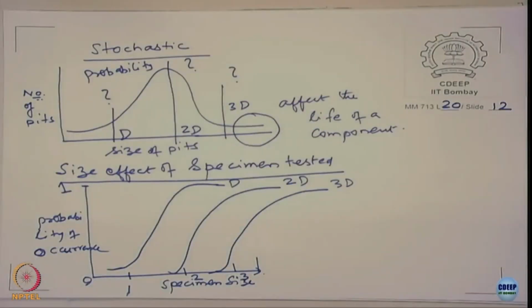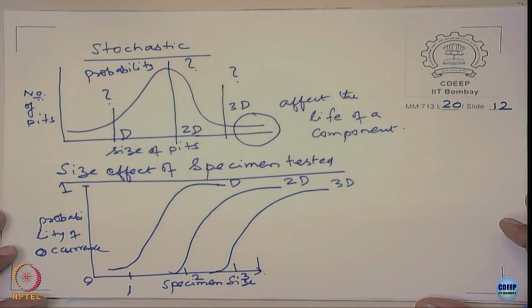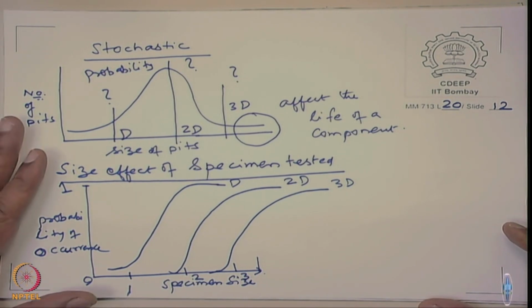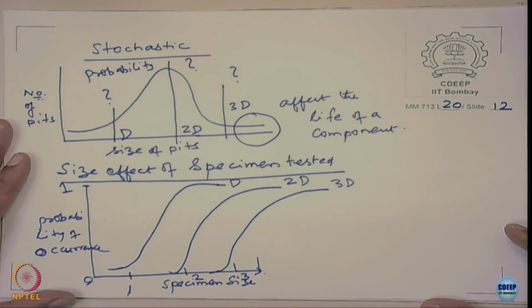So this is one aspect, and people have in fact dealt with this. The probabilistic theory of pitting corrosion has been one of the important topics of research. We will not go into more detail on it. The idea is to expose you to the complexities involved in determining the pitting tendency of any sample. So that is why when you do a test, especially a corrosion test, you give all information: size of the samples, environment, duration, temperatures, because there are several factors that affect the corrosion behavior of the metal. In this case, the size becomes even more important and relevant for us to consider. So that is something you should look at.